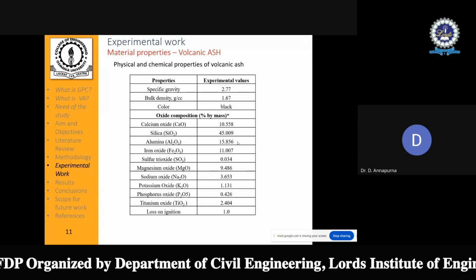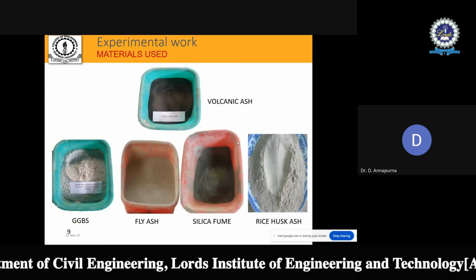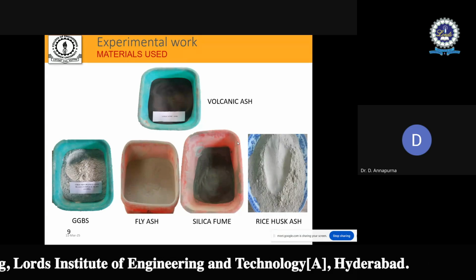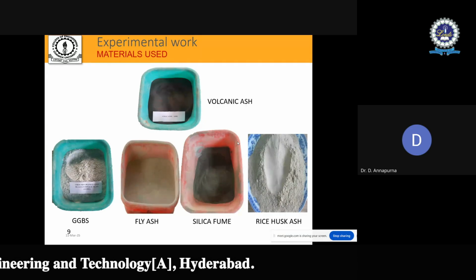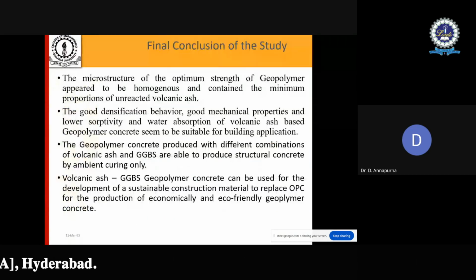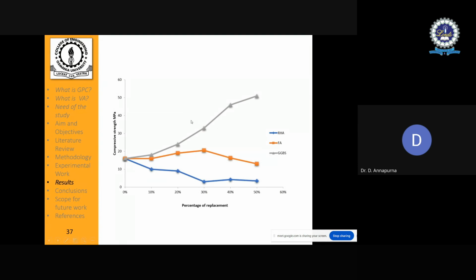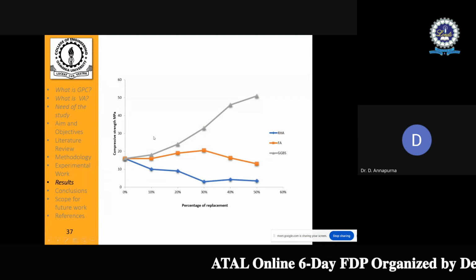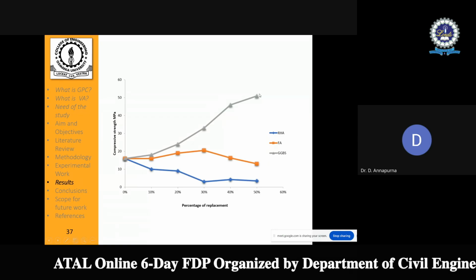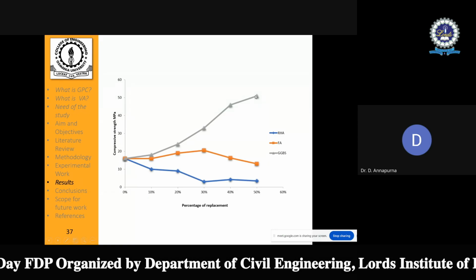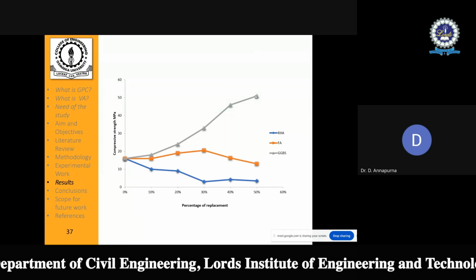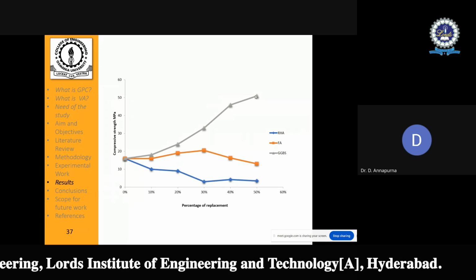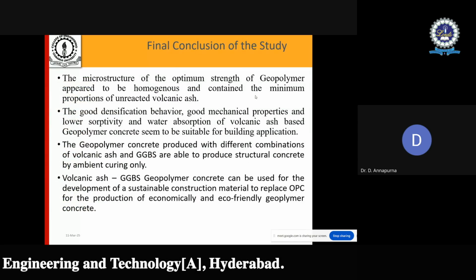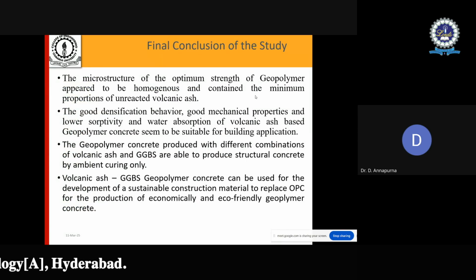That is, we are trying to get volcanic ash based geopolymer concrete with all these additives like GGBS, fly ash, silica fume, rice husk ash. Out of this, we identified that GGBS, when it is added as partial replacement with volcanic ash, is giving the highest improvement in the strength. Then behind this will be the calcium content. Calcium content is improving the strength property of geopolymer concrete. Final conclusions of the study is the microstructure of optimum strength of geopolymer.